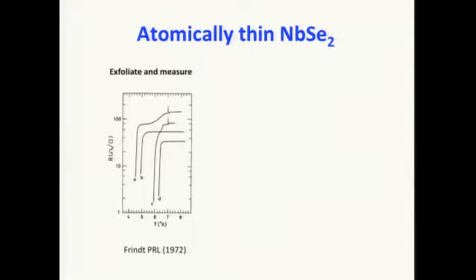So a little bit of history of how people attempted to get to a single layer of niobium selenide. It begins with this paper in 1972, by Frindt, a Canadian physicist from Simon Fraser University, British Columbia. What he did at that time is that he just used tape to exfoliate very thin layers of niobium selenide and directly measured the conductivity of this material. And as you can imagine, the material is highly inhomogeneous on the surface, with all sorts of different thicknesses. And he saw the superconducting transitions down to very thin films. So he concluded in his paper that the material, even down to the monolayer limit, is very stable in British Columbia air. Okay.